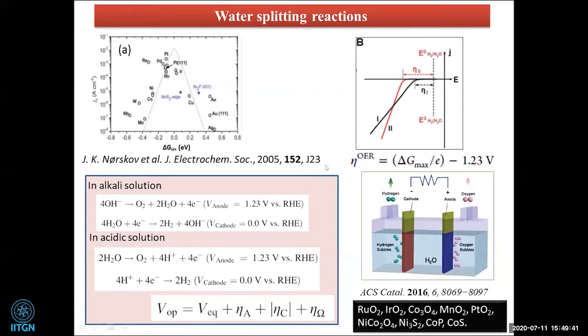Now we already come to know about the overpotential. Overpotential is the difference between the potential required to release the oxygen and the standard potential, that is 1.23 volt. So the aim of all researchers is to bring down the overpotential, whether it is the hydrogen evolution overpotential or the oxygen evolution overpotential. And these are a few of the best catalysts: ruthenium oxide, iridium oxide, cobalt oxide, manganese oxide. They are used for the oxygen evolution reaction.